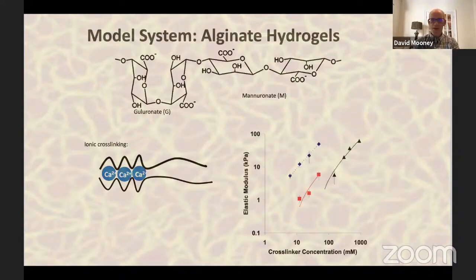Now, the system allows one to very easily and safely encapsulate cells simply by adding divalent cations to a solution. The cells become trapped in a three-dimensional matrix, and we can vary the stiffness of the substrate with the usual tools of polymer science: controlling the polymer molecular weight, the cross-linking concentration, or the composition of the polymer, the M to G ratio. As you can see here, we can get families of hydrogels in which we can very readily manipulate the stiffness, as indicated here by the elastic modulus.